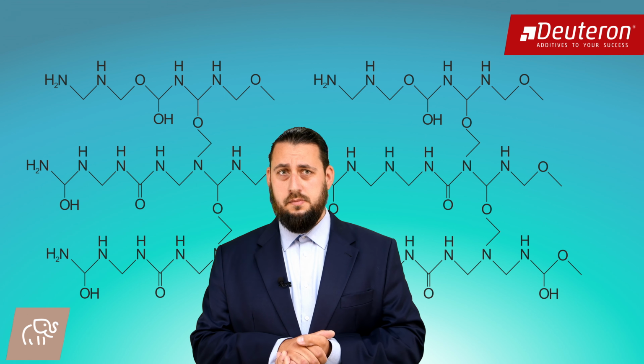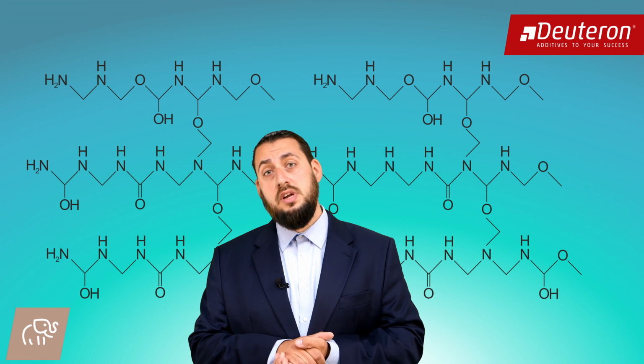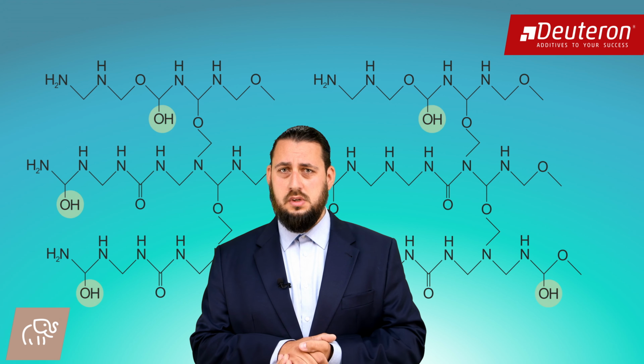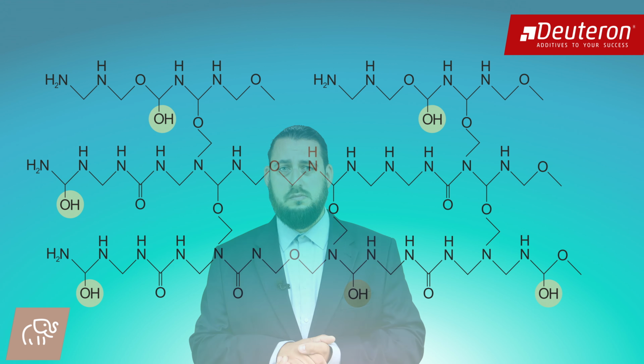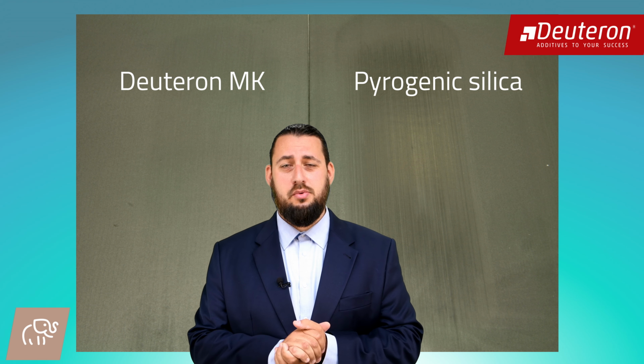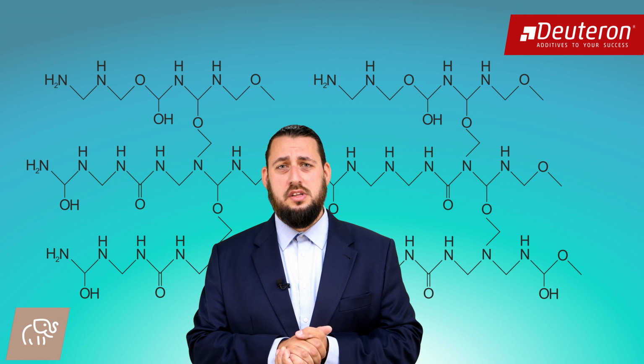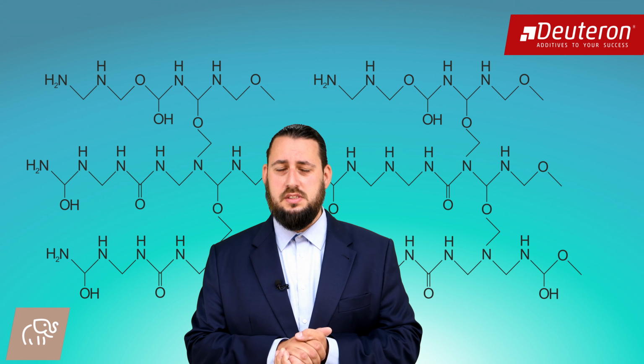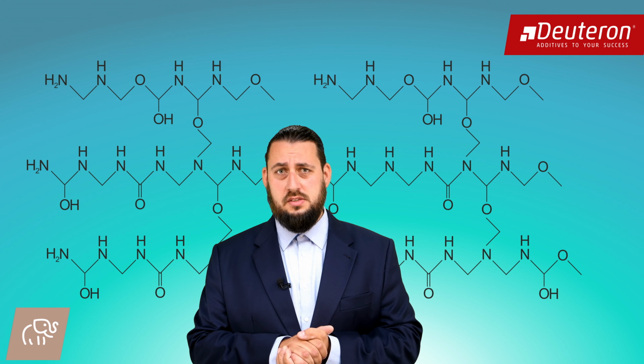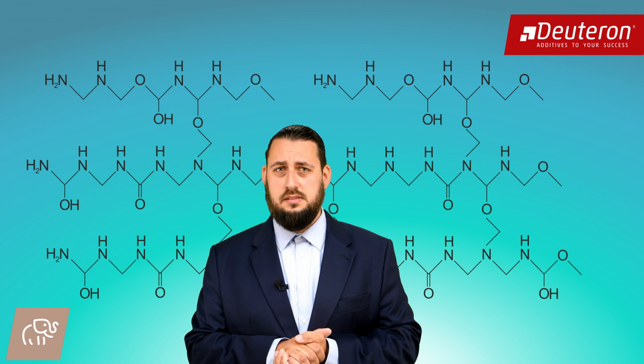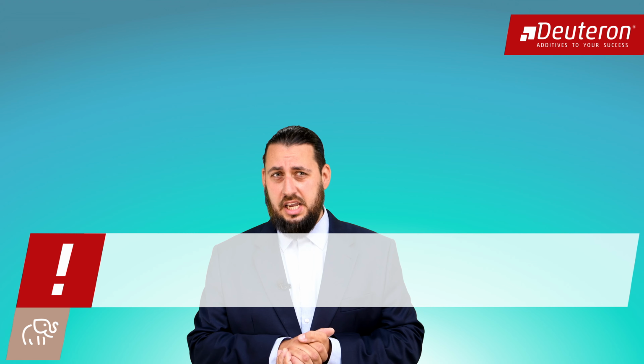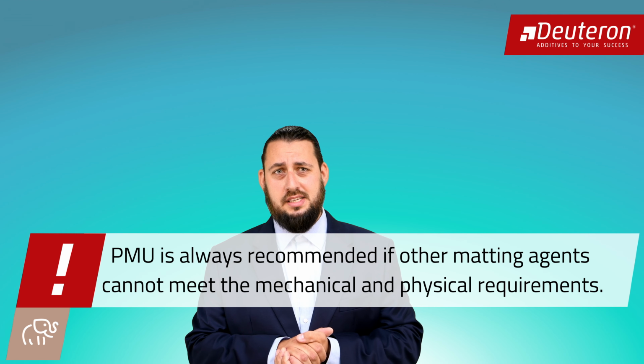The benefits are mainly: duromers have no softening or melting point. The temperature stability is up to 200 degrees Celsius and for short times above 300. The polymer contains hydroxyl groups and cross-linking with isocyanate hardeners is possible. PMU has a high hardness compared to other plastics. Therefore, high mechanical resistance against scratches and abrasion is possible. Unlike silica, our matting agents do not absorb catalysts in baking enamels or other reactive systems. In aqueous systems, PMUs don't absorb associative thickener. The viscosity remains stable. PMU also supports the effect of classic soft-touch coatings. Basically, you could say, the use of PMU-based matting agents is always advantageous when the properties of conventional matting agents are not enough.